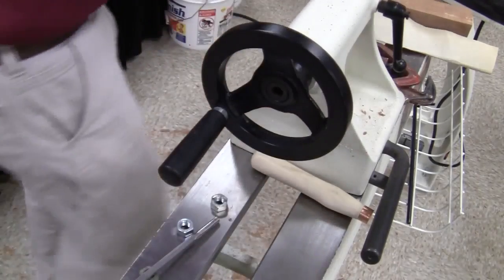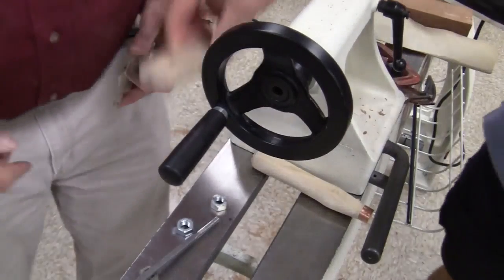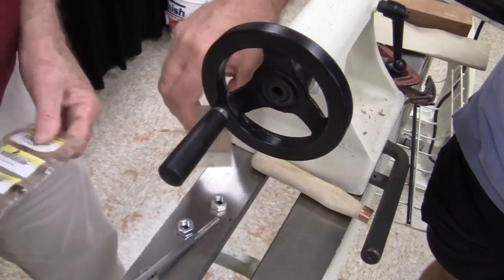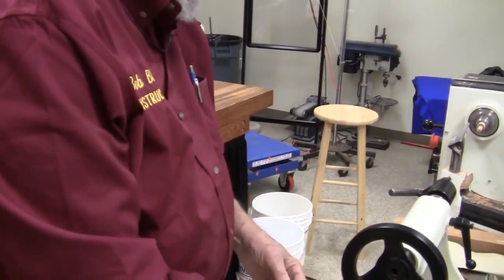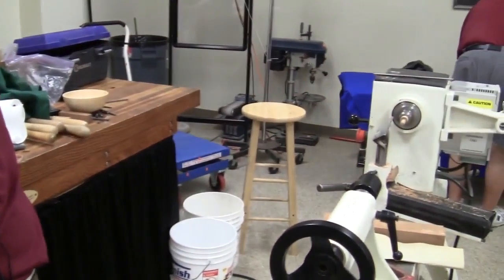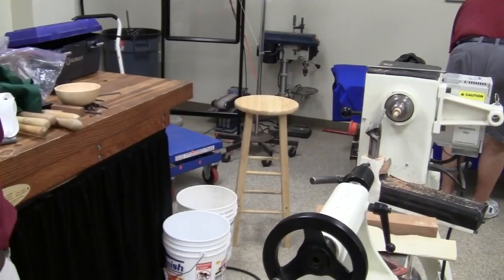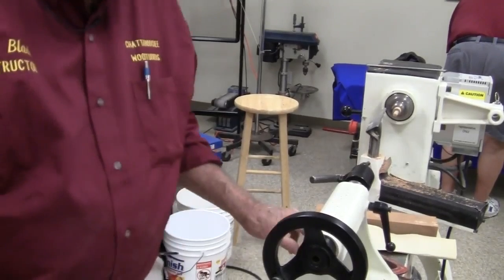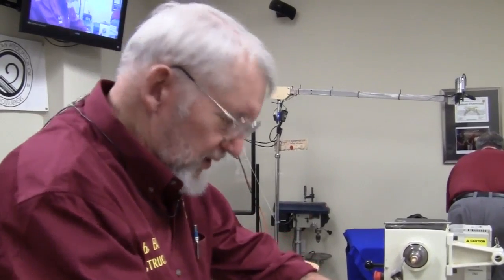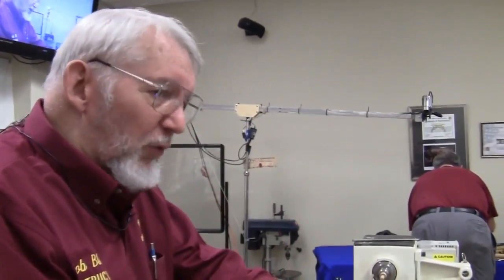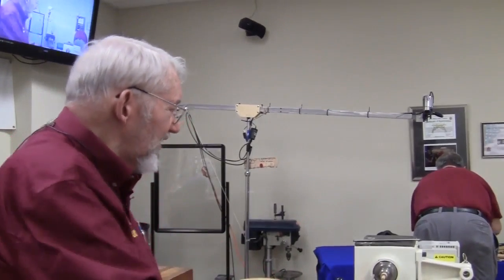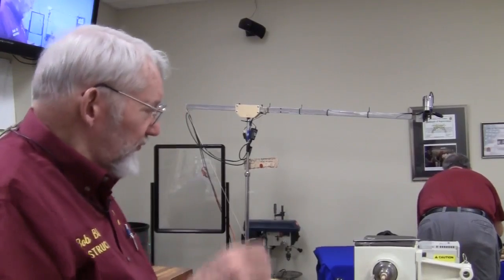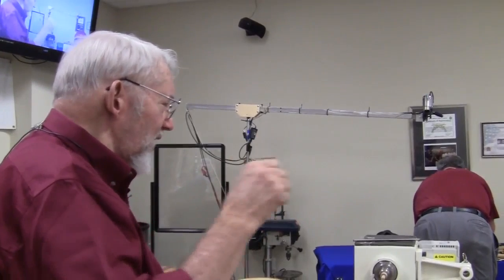Well, you can see what I've got. The short piece is what I'm concerned about. I'm not concerned about the long. The short piece, in that case, the braze was square, so you can clamp straight on it. They come 2.5, I cut them in half, and it's still way too long, but that seems to be the ideal, long enough to clamp and not waste too much steel, but not run into a heat sink problem. And this stuff, with even a pretty fine oxyacetylene tip, you can get them hot fairly quickly.